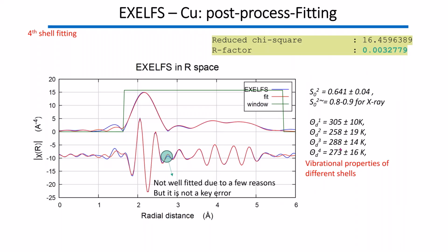The only difference is that there is a systematic reduction in the Debye temperature, because we are using the same foil where the lattice is a bit different, so the vibrational property or the lattice has been relaxed a bit. So in that sense, you would expect the Debye temperature to be smaller. Nevertheless, you can see the Debye temperature changes according to different shells, which means you cannot approximate this atomic vibration as a purely harmonic oscillator. You have to include this anharmonic effect, and this can be a very good input when you want to refine the first principles potentials.